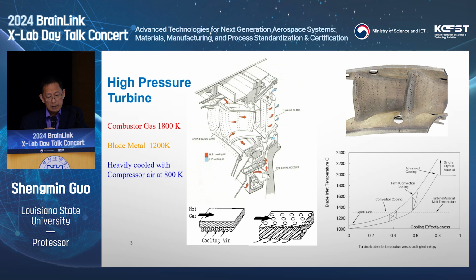So what you will find, in order to safeguard jet engine components, is that you have to add a ceramic layer on the surface to provide a so-called thermal barrier coating. And inside, we have to think of introducing cooling jets, using cooling gas to provide cooling to make sure that all the engine hardware doesn't exceed the allowed temperature. The nickel-based super alloy, even the single crystal one, has a maximum temperature probably less than 1,000 degrees C. 1,000 degrees C apparently is not hot enough to operate a jet engine. So the idea is near the wall, you make sure the temperature is at or below 1,000 degrees C. Away from the wall, you want the temperature as high as possible.